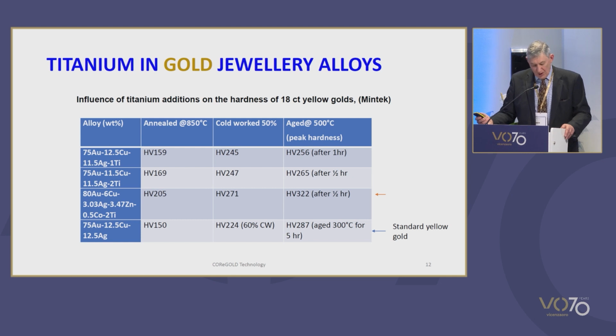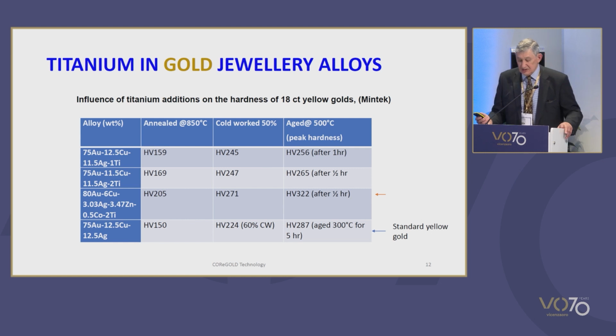They attributed the poor hardenability of the alloys to the increased solubility of titanium due to the copper and silver content of the 18-carat gold. And this reduces the amount of precipitate that forms and hence limits the potential increase in hardness and strength.